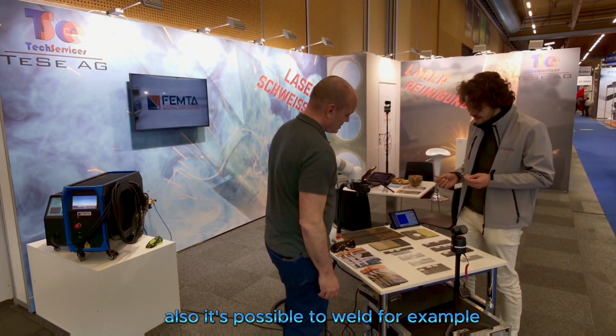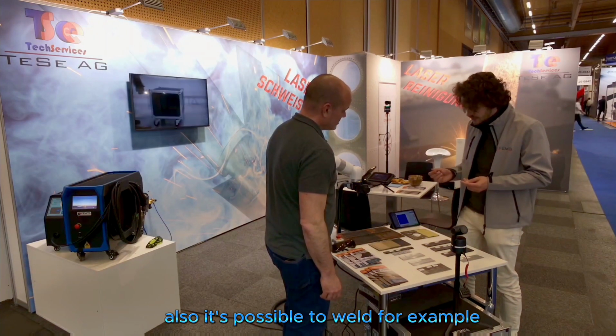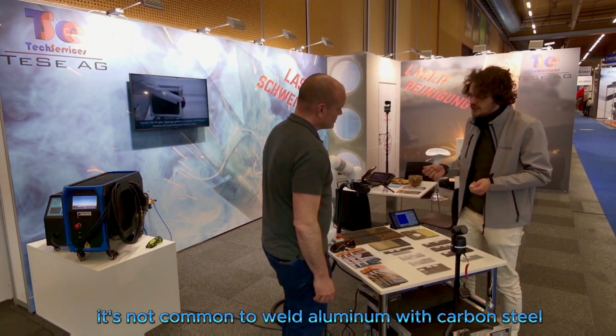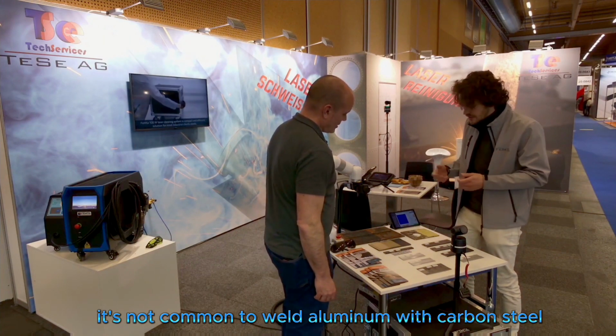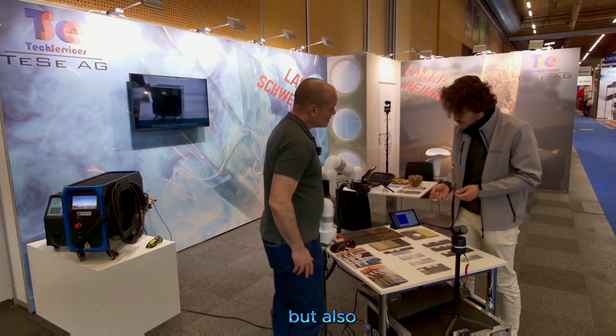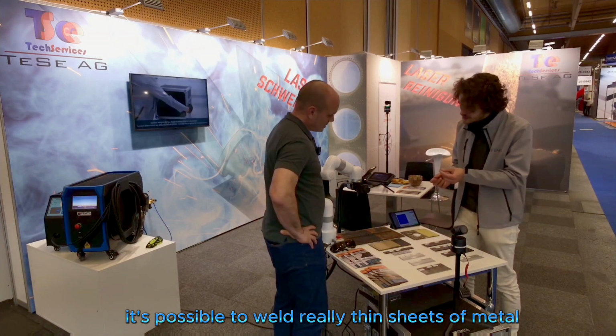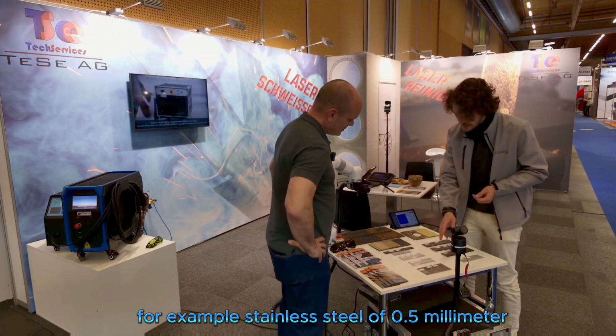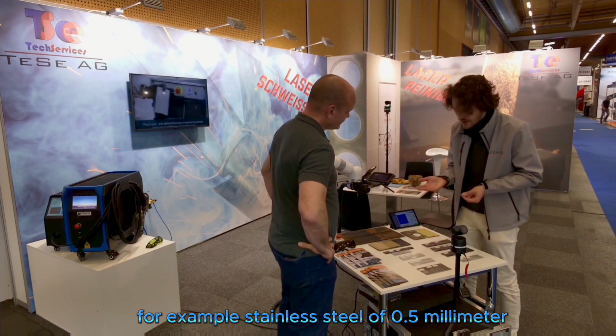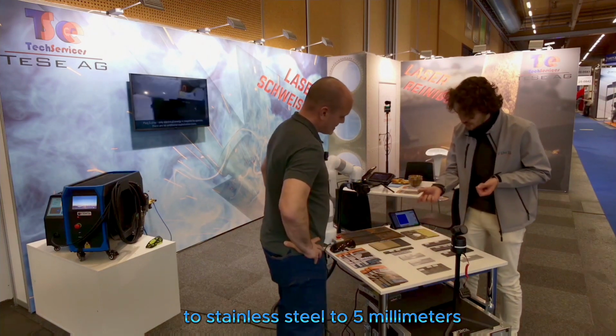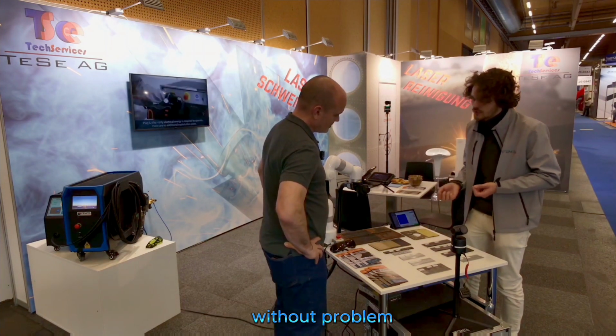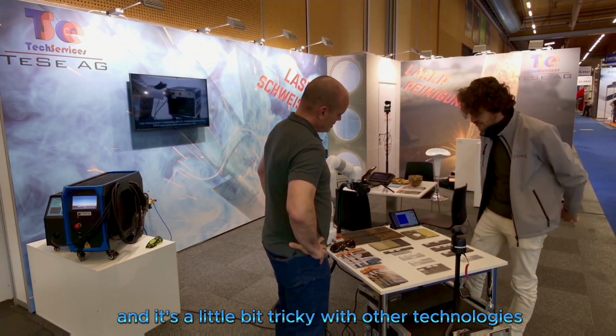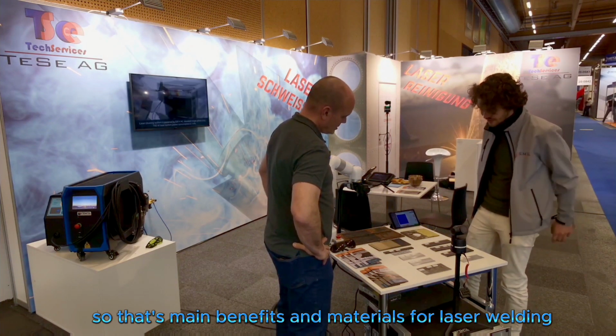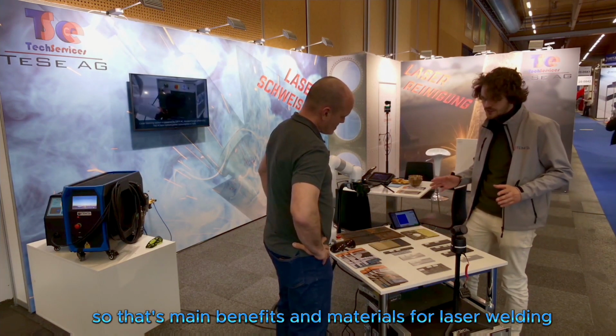Also, it's not common to weld aluminum with carbon steel, and it's possible to do it. But also it's possible to weld really thin sheets of metal. For example, stainless steel of 0.5 millimeter to stainless steel of 5 millimeters without problem. And it's a little bit tricky with other technologies. So those are the main benefits and materials for laser welding.